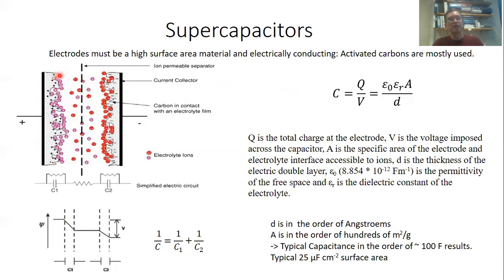Okay, so the negative charges cannot hop basically into the electrode material. Therefore, we still have capacitance and not a redox process. Therefore, they must be separated by a certain distance from each other. But that distance is now, of course, extremely small. It's in the order of a fraction of a nanometer.